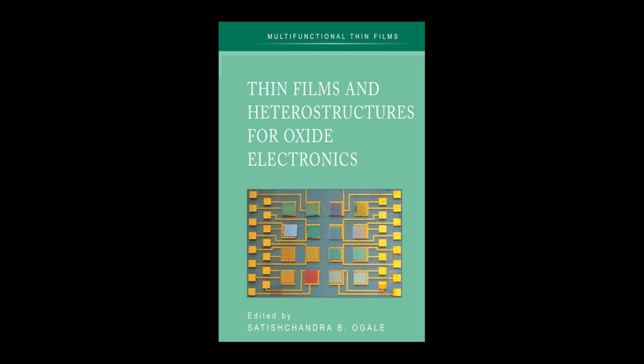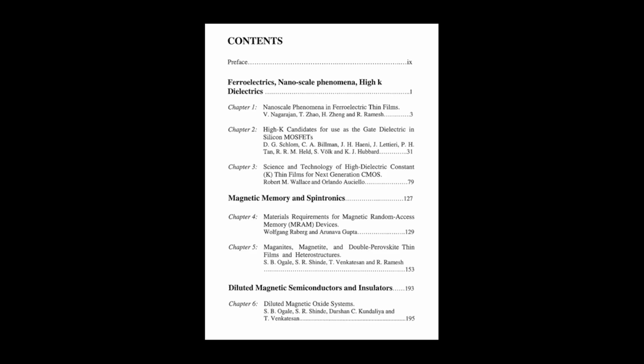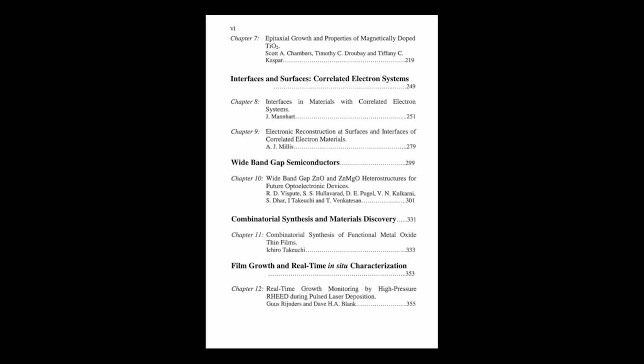But, like with most complex oxides, actually growing high-quality ZnO films, especially using pulsed laser deposition, PLD, turned out to be a tricky optimization problem. What was the main trade-off they ran into with PLD growth of ZnO? It came down to the oxygen pressure in the growth chamber during deposition. There was this fundamental conflict.